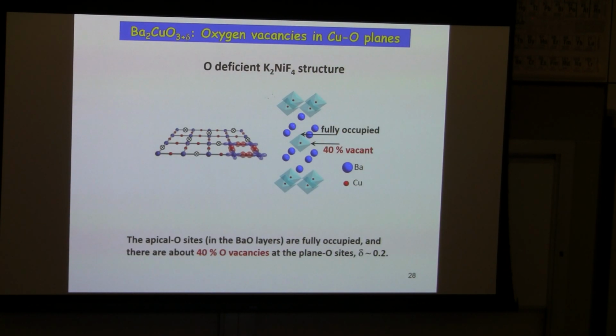And a more surprising fact: in this cuprate, there are a lot of oxygen vacancies. In the conventional cuprate, oxygen vacancies exist out of the copper oxygen plane. But in this new cuprate, the copper oxygen plane is highly oxygen vacant. That is quite crazy in view of the conventional cuprate. But nevertheless, this is true, evidenced by neutron diffraction experiment. You can see that almost 40% of in-plane oxygen sites are vacant. That is a very crazy cuprate.